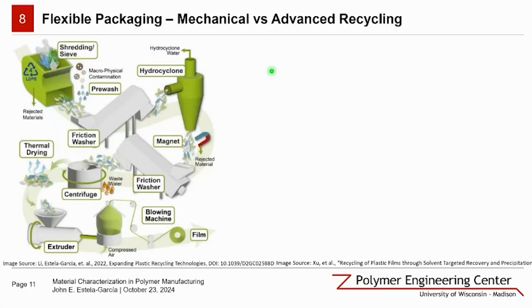So we can look at how some of these recycling techniques tackle one of the biggest problems, flexible packaging. Packaging is a major source of single-use plastic waste and presents unique challenges in recycling. From the inks and the adhesives that are used to the presence of multiple layers of different plastics, there's a lot that goes into recycling some of these materials. So right on the left, I'm showcasing an infographic that's demonstrating the mechanical recycling process for pure LDPE films. This is something that you could expect to be occurring at a MRF. So it's a multi-step journey.